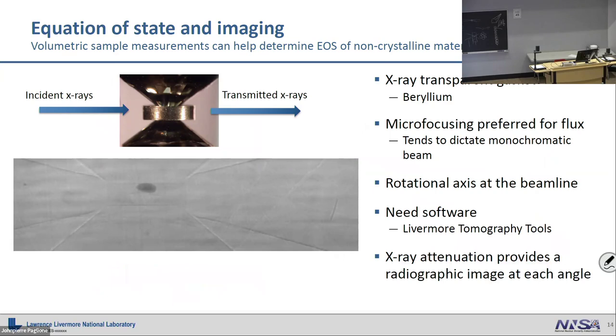There's another technique that people use. They don't use it as much with crystalline metals, but for things that are amorphous, you can't get diffraction off of them. So you can get some sort of scattering, but it doesn't necessarily tell you all the volumes. How you map the scattering of an amorphous thing back to a volume is a little trickier. So one of the techniques that's been developed is tomography.